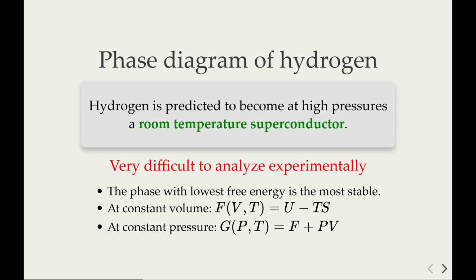This is a very interesting problem because hydrogen is predicted to become a high-pressure superconductor, and in particular a room temperature superconductor. This prediction was made in the 60s by Ashcroft. However, it is extremely challenging to synthesize pure hydrogen at very high pressure, and it is even very difficult to analyze this sample experimentally because it does not interact with most of the probes we have that work at high pressure.